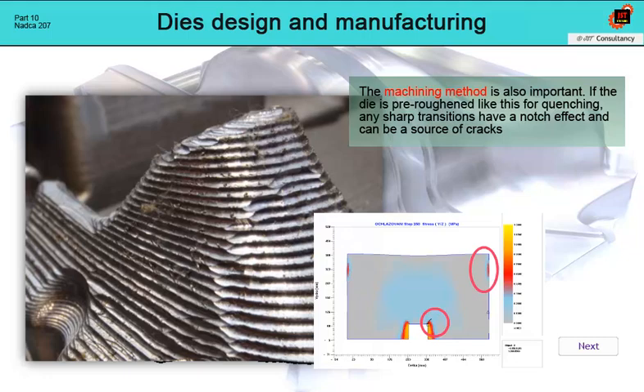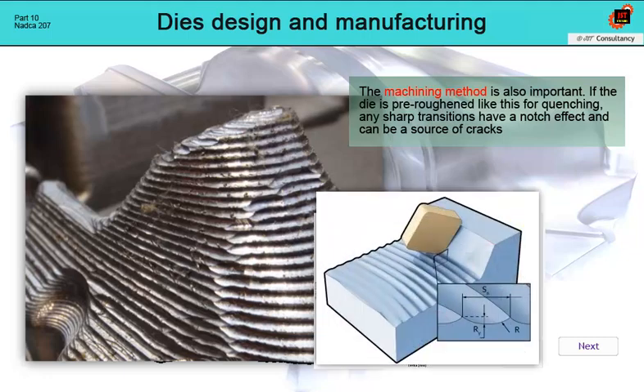With a surface prepared in this way, it is obvious that basically every trace of the milling cutter can mean a notch effect with a concentration of tensile stress. Since today, the majority of processing is solved digitally in graphic design software, with subsequent data transfer to CNC machining centers, it is not a problem to ensure a simulation of the result and correct the program even before the actual machining is carried out.